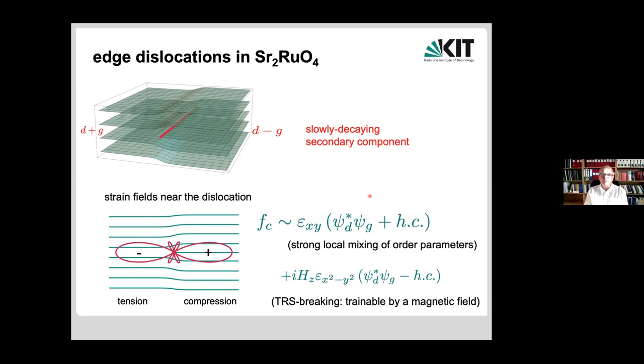Yeah, what matters is the induced strain at the step edge. Ultimately, that's what we need. And the way I understand it is that the induced strain at the step edge is significantly smaller than at a dislocation. So it may come down to an issue of numbers. I don't think that you get quite as large strain values there, and you need that, unless, of course, these two states are really almost degenerate, and then it should work. So it may be a matter of details whether or not. My suspicion is rather not.